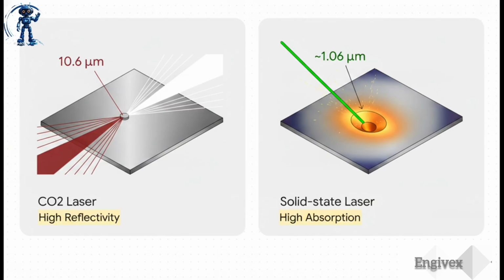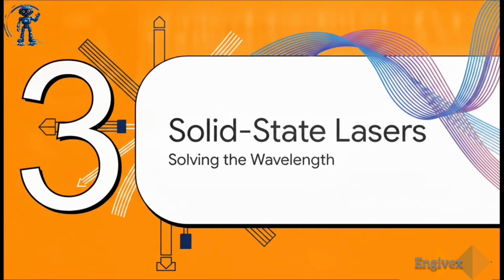Okay, so what was the actual root cause of the CO2 laser completely failing with aluminum? It all comes down to one thing: wavelength. Gas-based CO2 lasers operate at a wavelength of 10.6 microns, and aluminum is highly reflective at that relatively long wavelength. But look at solid-state lasers, they operate at around 1.06 microns. Because absorption increases as the wavelength decreases, aluminum absorbs roughly 3 times as much laser energy at 1.06 microns as it does at 10.6. Using those old CO2 beams was practically like shining a flashlight at a mirror and expecting it to melt. Which brings us nicely to Section 3, Solid-State Laser Breakthroughs.